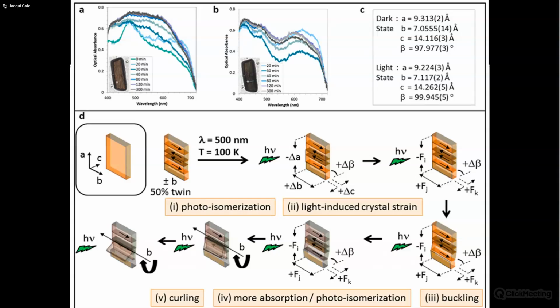So I could get the optical absorption of the point in the white circle there, which is where you get that cut. You see the next slide B, where the white circle now is literally inside the bit that's cut. So that's in some form a sort of shallower part of the crystal, right? Because part of the crystal's opened up. So you should get less absorption, and you do. In fact, at that very point, your optical absorption spectra is much more corresponding to the light-induced state without the saturation that we're getting on the left. Right, you see that peak is much more saturated, and that's because you're going through a thicker crystal, right? And you've got all this sort of effect of the peeling on top of it.